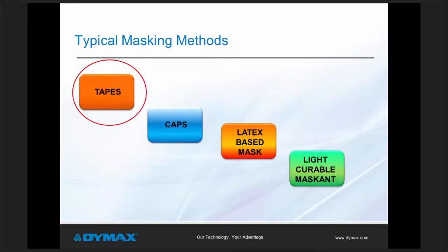Just as we learned there are different types of conformal coatings, there are different masking options for the protection of the connectors and the board keep-out zones. First, let's talk about tapes. As we saw in the results, many of you are currently using tapes. Tapes and dots are a very common method, which do not require a curing step, but they are a very labor-intensive application, especially on highly populated boards where there's very little space between the connectors to be able to achieve a good seal against the board. Tapes also bring some challenges of removing the residue left after the coating has been applied and heat cured. This could be the root cause in not passing the SIR testing on the boards.